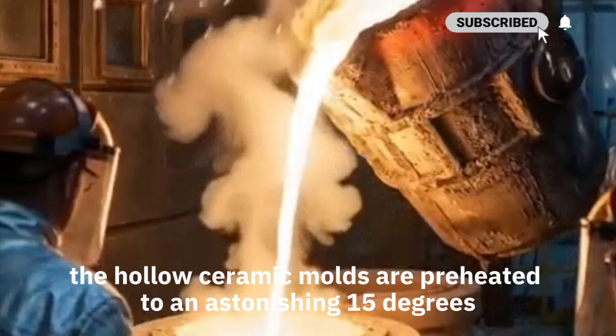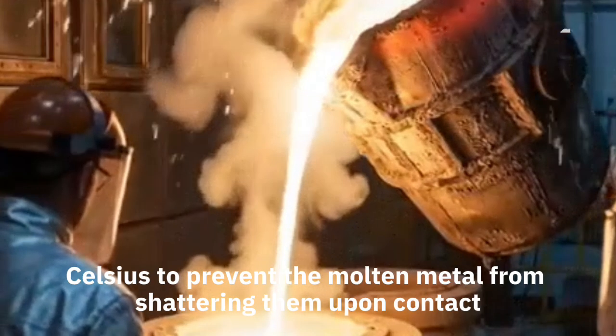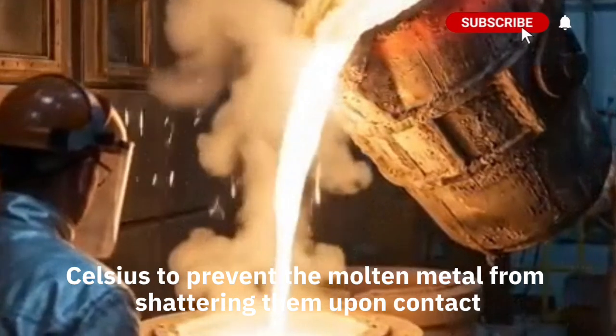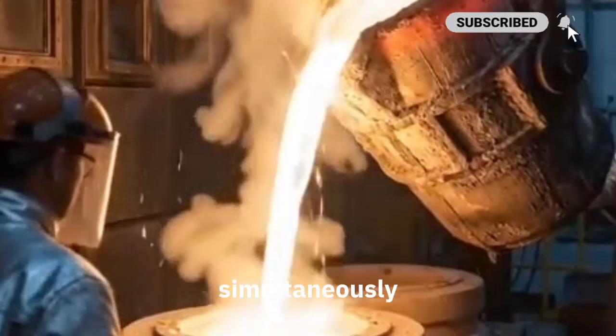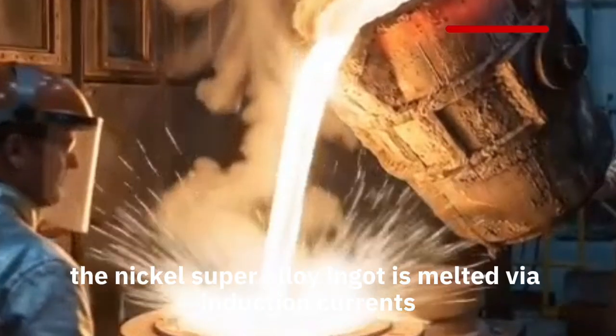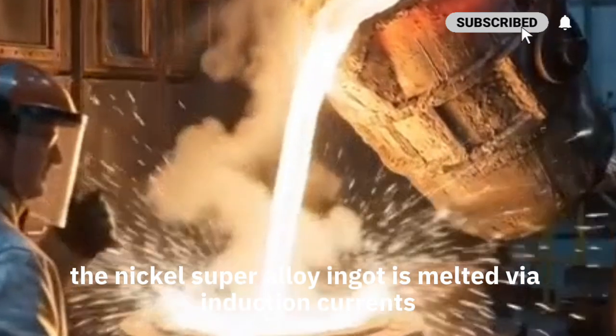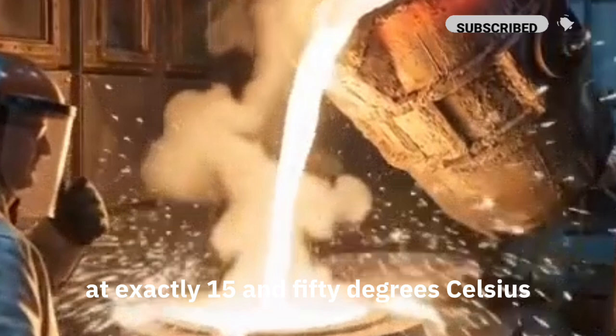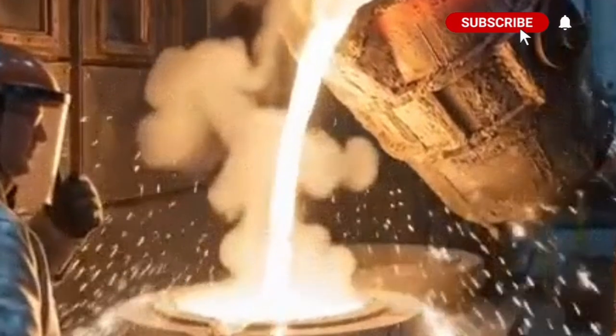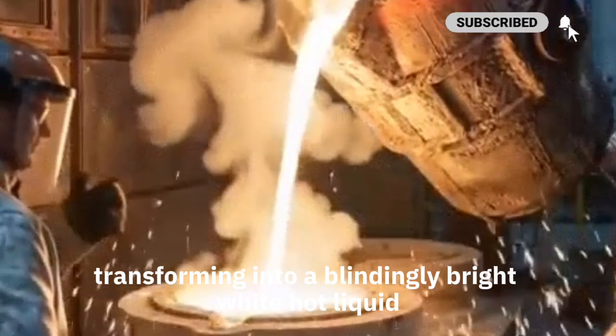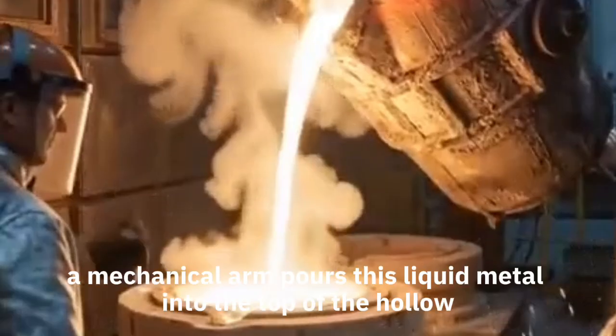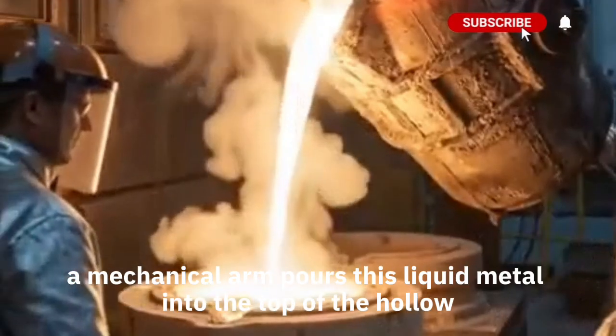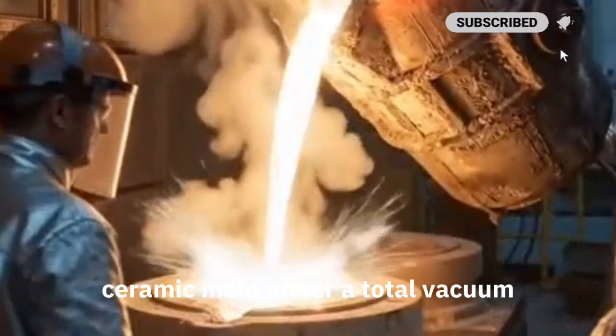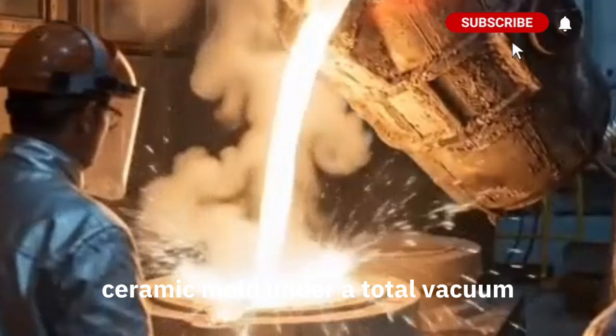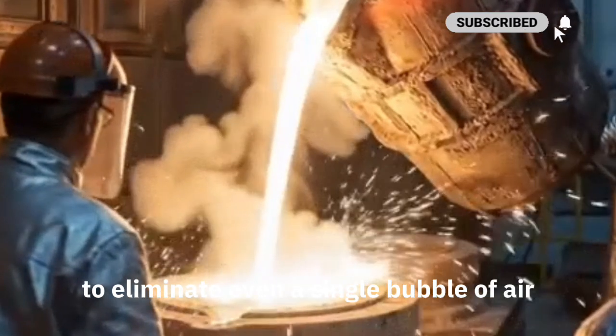The hollow ceramic molds are preheated to an astonishing 1,500 degrees Celsius to prevent the molten metal from shattering them upon contact. Simultaneously, the nickel superalloy ingot is melted via induction currents at exactly 1,550 degrees Celsius, transforming into a blindingly bright, white-hot liquid. A mechanical arm pours this liquid metal into the top of the hollow ceramic mold under a total vacuum to eliminate even a single bubble of air.